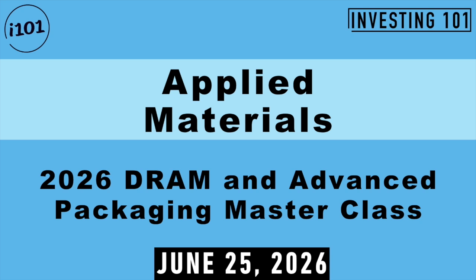Integrated hybrid bonding reduces the queue time between the critical activation and bonding steps, which preserves bonding integrity and improves bond strength and yield. The enclosed system minimizes particle contamination, which is critical because hybrid bonding uses known good dies and needs to be nearly 100% defect-free. Our integrated metrology makes sure the chips are perfectly aligned. Kinex is designed to help expand die-to-wafer hybrid bonding from a high-end niche application to the mainstream.